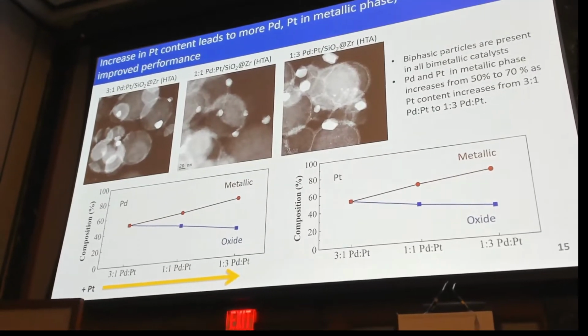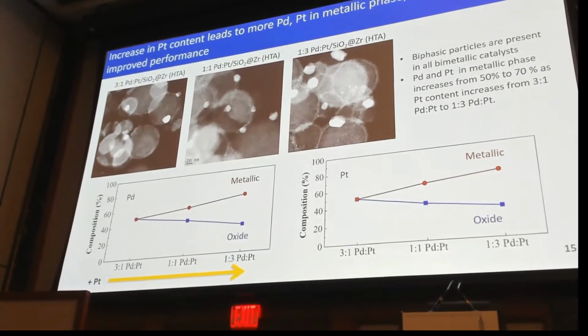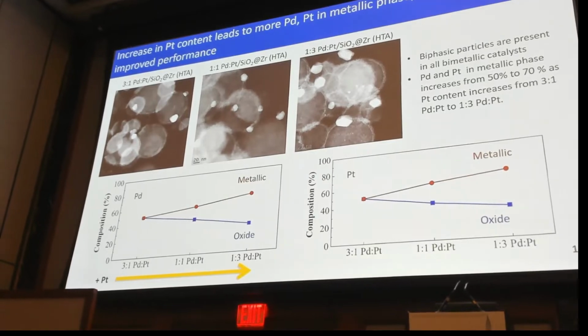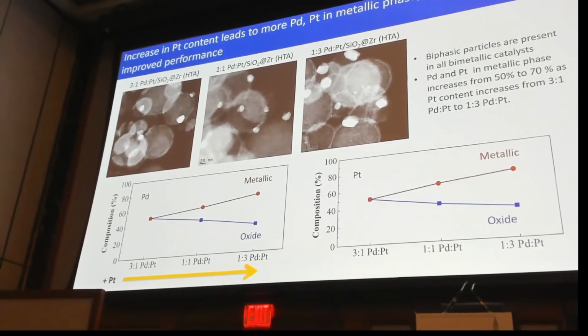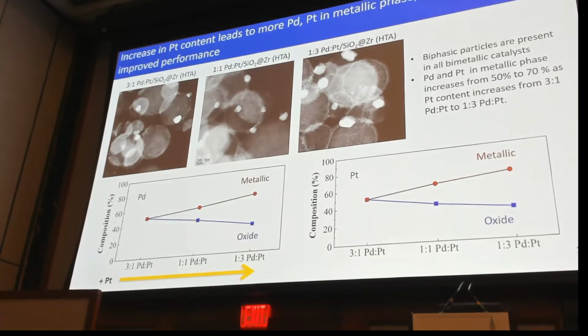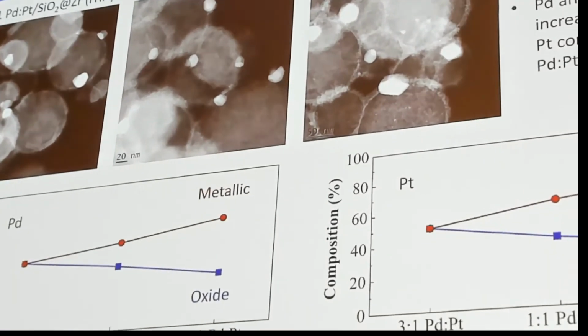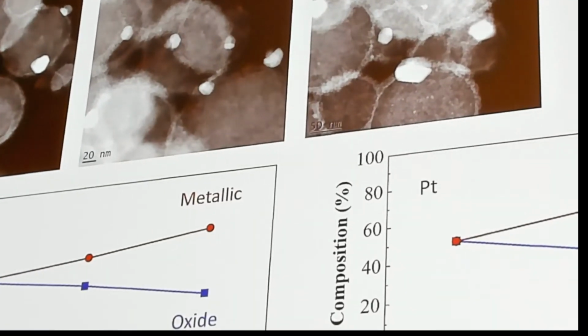So the right figure shows the platinum composition again over the three bimetallic catalysts. And what we see again is that in the biphasic particle, 70% of platinum is in the metallic phase and 30% of platinum is in the oxide phase. Okay?